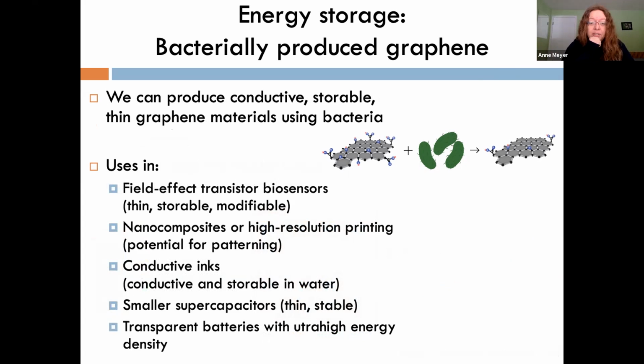So this could be a really interesting way to make biosensors. So something, for example, like a sticker on your skin that's very thin and flexible, and is stable over a time frame of weeks or months, that can, for example, detect how much glucose is in your blood, right? We also didn't show today, but we have techniques where we can pattern the graphene. So for example, if you have your graphene flakes, you can have it be reduced on one side and not on the other, right? That makes it easy to self-assemble into composite materials. Or for example, you can print in high resolution.